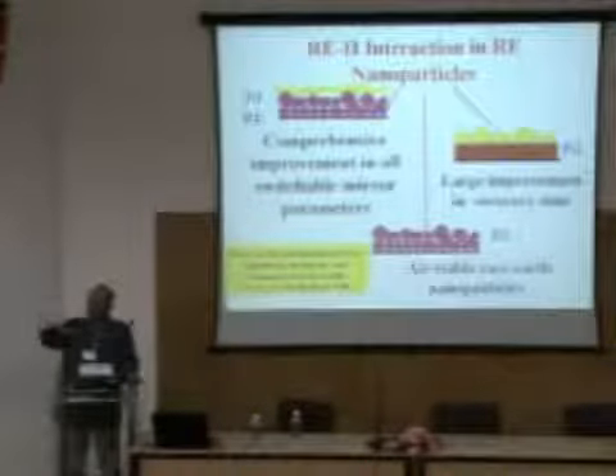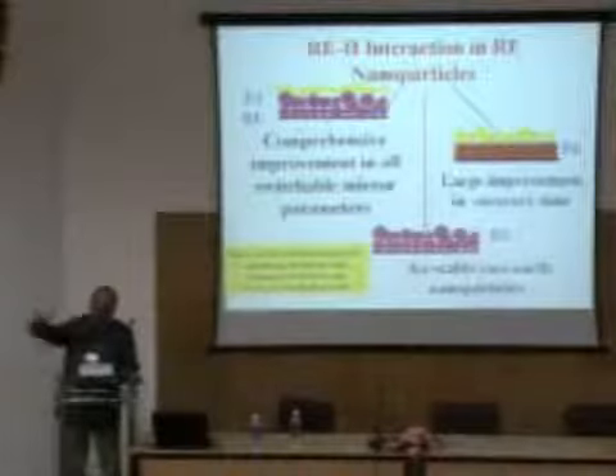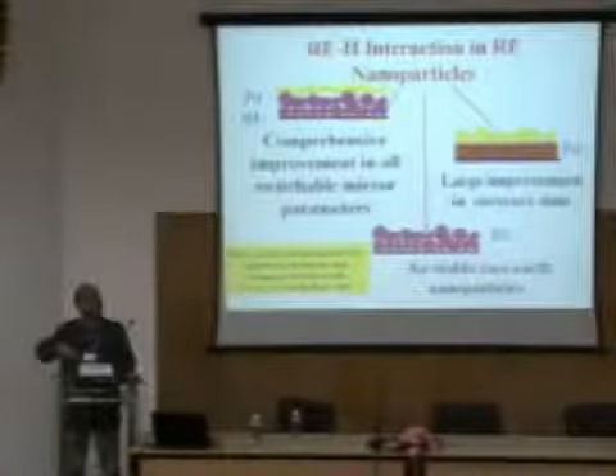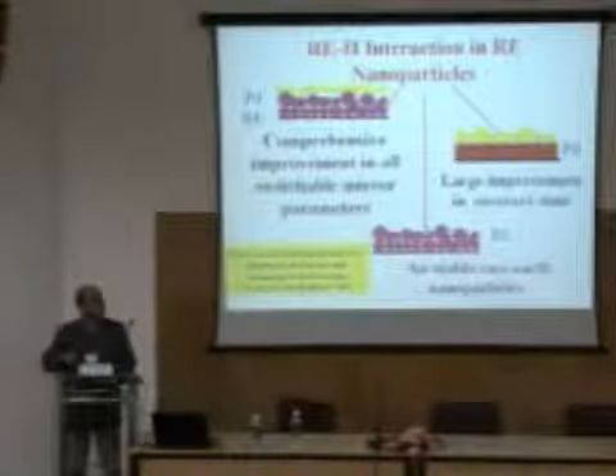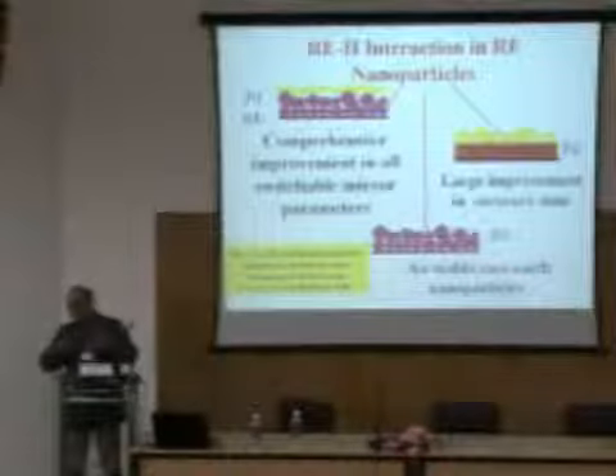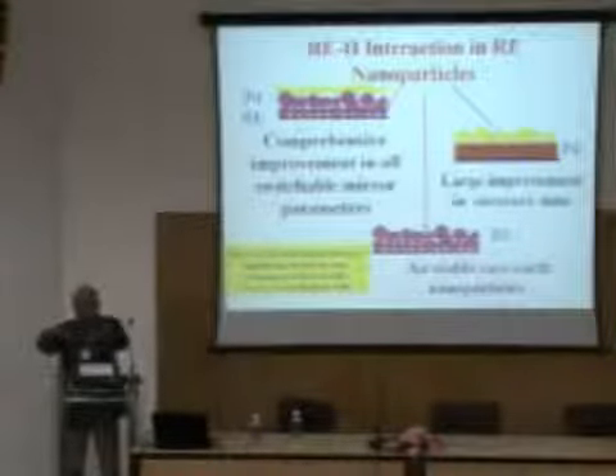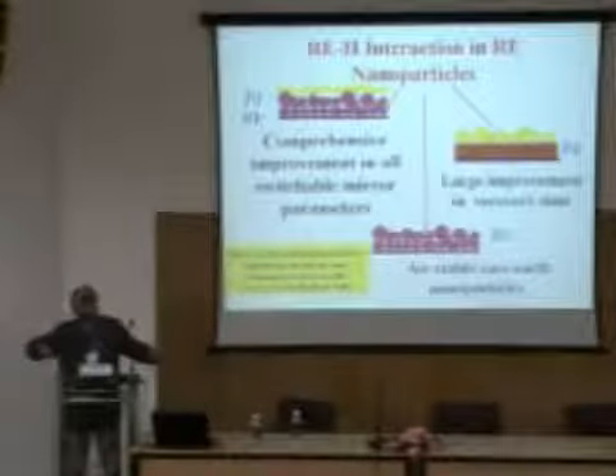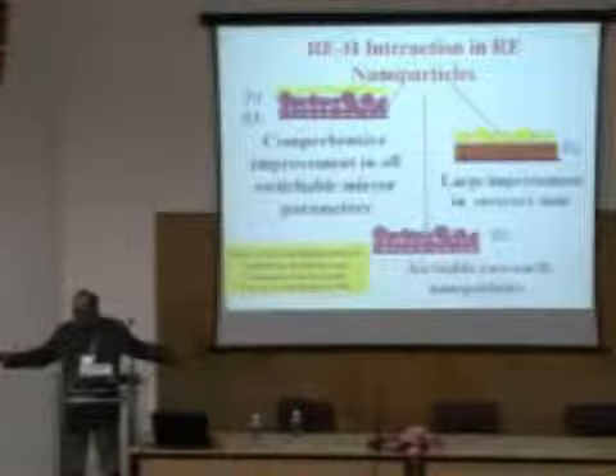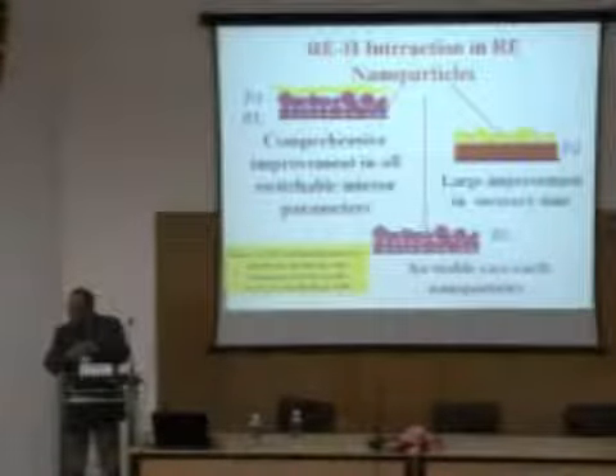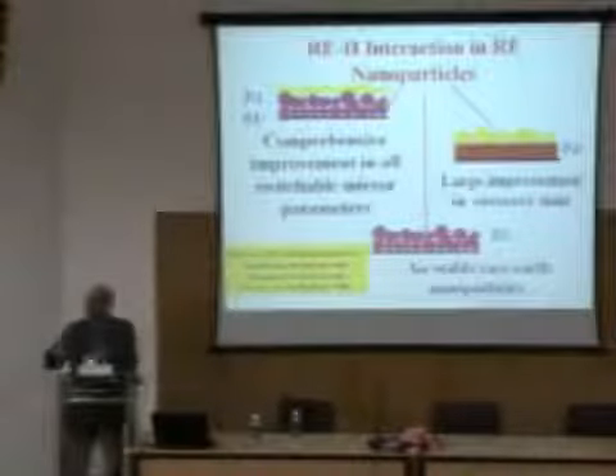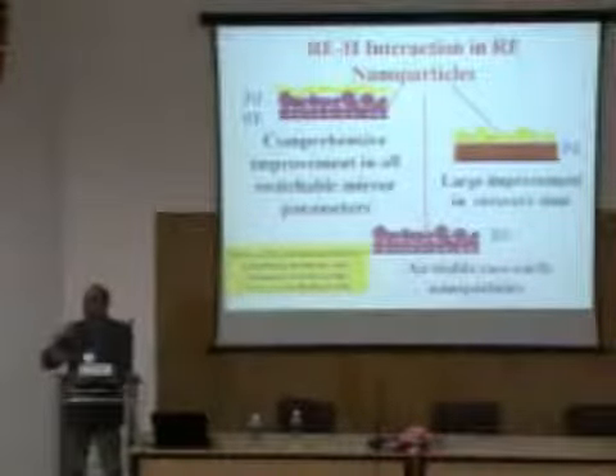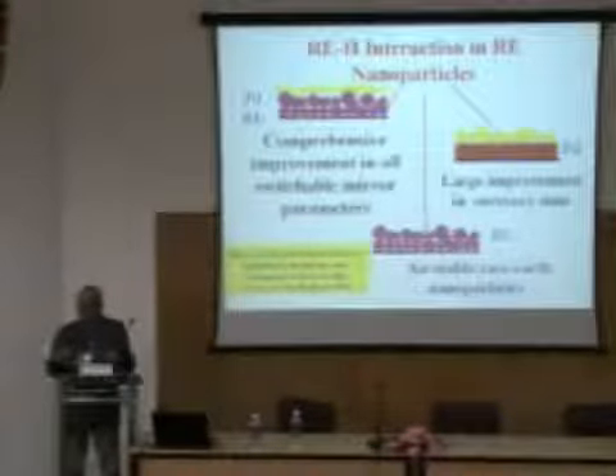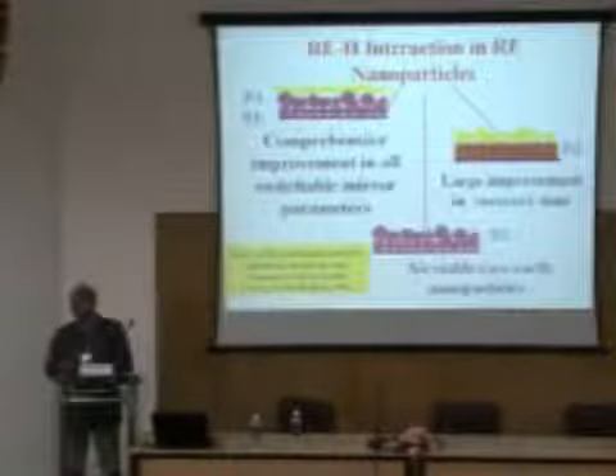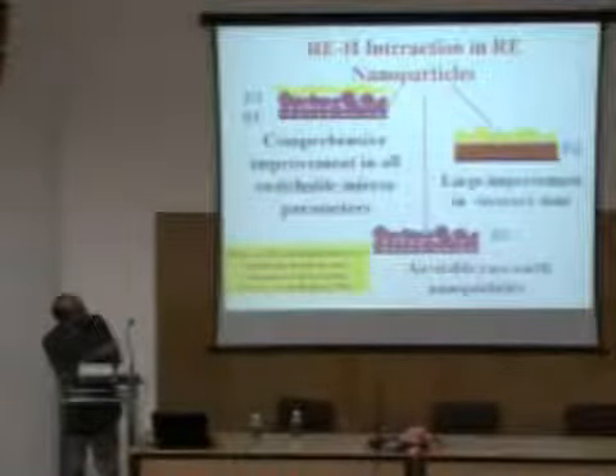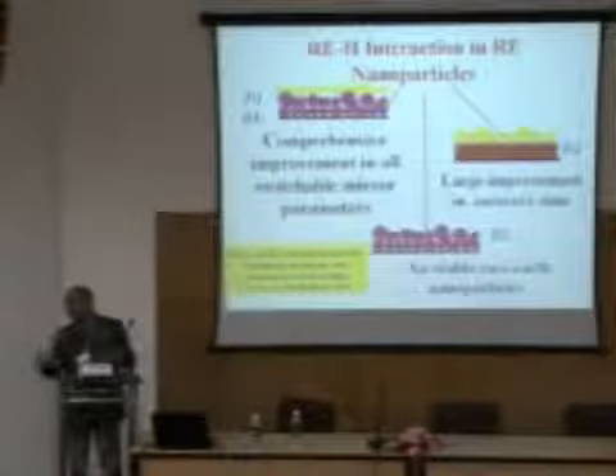Whenever hydrogen is going in, it goes very fast, but the hydrogen removal is very slow. This is true for all sensors on all kinds of materials which interact with gases. It is easy to understand: when a hydrogen molecule is going in, it goes in at one palladium site and gets converted to 2 atoms of hydrogen. But when the hydrogen has to come out, 2 atoms have to come together at a particular site and combine, so thermodynamically and also kinetically it's a slow reaction. So the recovery times are always slower than the response time. And in this case, it was very nice to observe that the recovery time can be improved by changing the palladium thin films to palladium nanoparticles. And you can see that all the results are very dramatic.